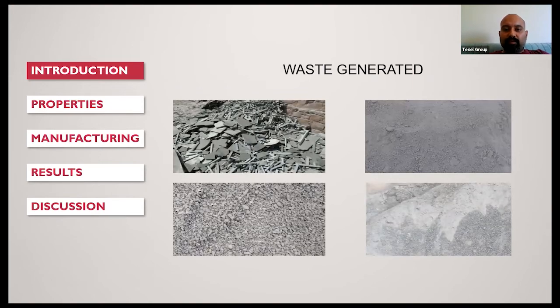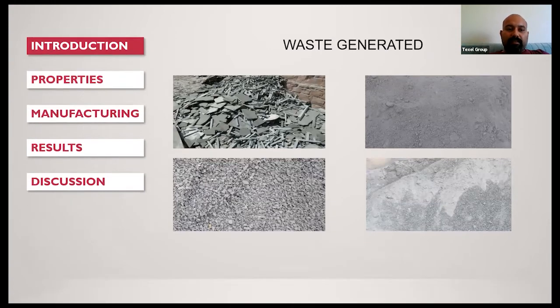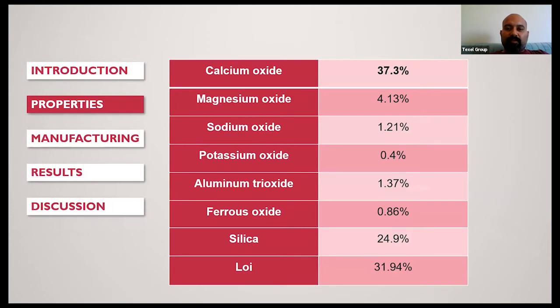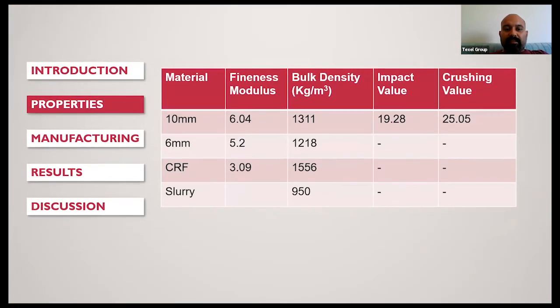These are pictures of waste generated through Kota stone; the first shows waste in the form of boulders, which is crushed into 6 mm and 10 mm sizes, and the last picture is of stone slurry. These are the basic properties of Kota stone waste, which primarily consists of calcium oxide at 37.3%. I manufactured the waste in two forms: 10 mm and 6 mm as coarse aggregate, and crushed rock fine mixed with the slurry.